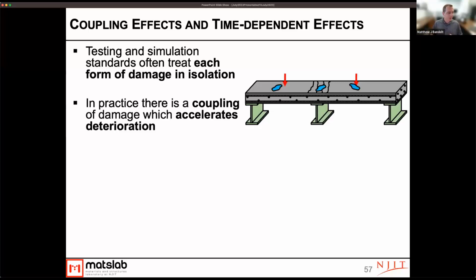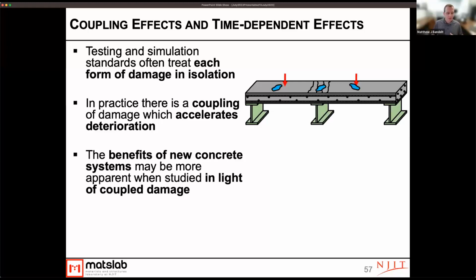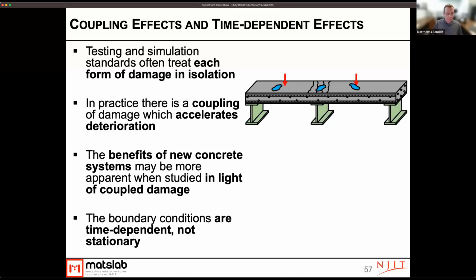But we know that there's this coupling that happens, and Matt went through some of the chloride profiles of cracked specimens, right? And what you could see was, in the cracked specimens, we showed that there was the propensity for some of this corrosion to potentially occur, whereas in uncracked specimens in the same time frame, we never saw that. And so the benefits of some of these new concrete materials might be more apparent when we study the coupled forms of deterioration. And we also have to think about the fact that boundary conditions are time dependent and not stationary.